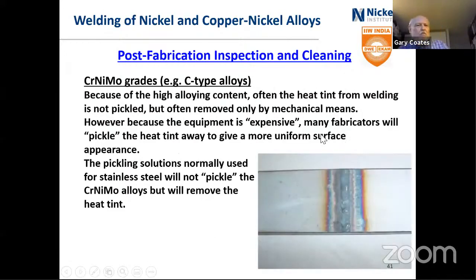Now, one of the questions that comes up regularly is, because of high alloying content, do we need to pickle the heat tint from the welds? And the laboratory scientific answer is that no, you do not, because the services that most of these are going into will actually dissolve any heat tint, any chromium depleted zone beneath the heat tint. So often they're removed only by mechanical means, a stainless steel wire brush.